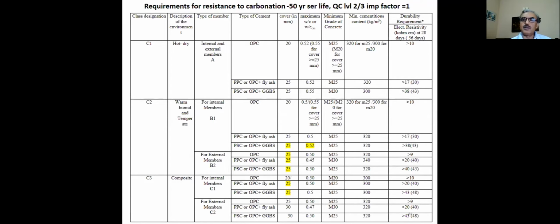Other tests can also be used. Even at this stage, we will be permitting that other tests like oxygen permeability, bulk conductivity, bulk resistivity can be used for quality control purposes. For example, you do a mix stage, you achieve these values of the electrical resistivity, and you do additional tests which you want to use for quality control purposes. And what will be the acceptance criteria of those tests, that we will cover in the quality control chapter. So you can do oxygen permeability test along with this, and then you can achieve those values in the field. So that can also be permitted.